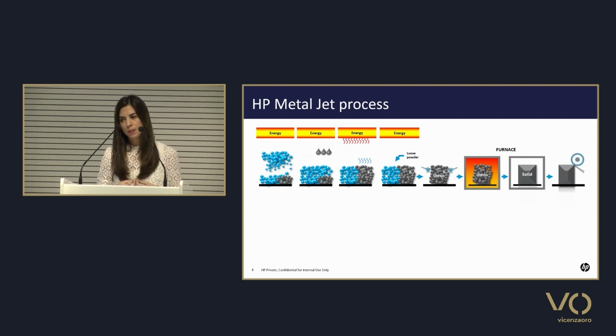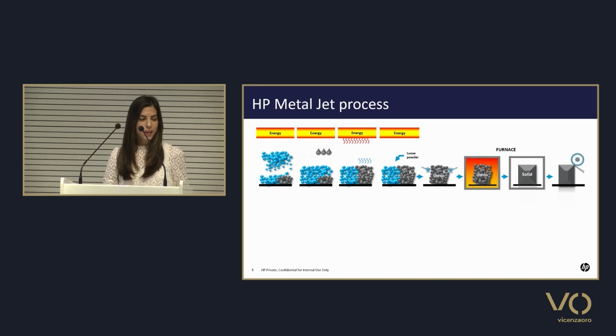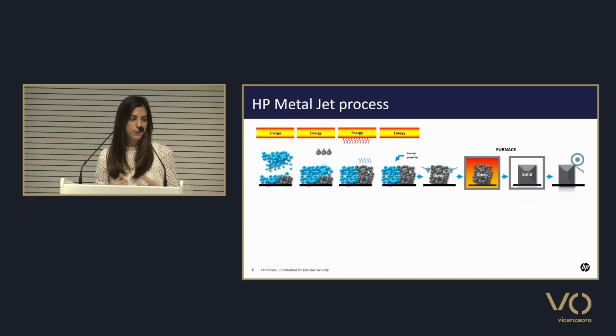The ink that we deposit in this technology, we call it a binder, which is basically a glue that glues the metal particles together. So we keep on doing this layer by layer. You spread another layer of powder, you put the ink again using our print heads, and you need to do this while applying a certain level of energy. You need to apply a little bit of energy because our ink is a water-based ink, and you need to start evaporating part of the solvents from this ink. Also, it's important to apply energy because you don't want the ink to go into further layers. You want the ink to fix in the layer where you are printing at that exact moment.